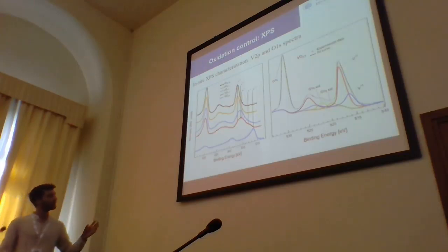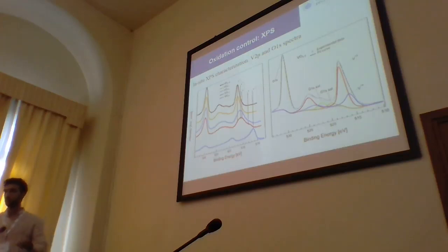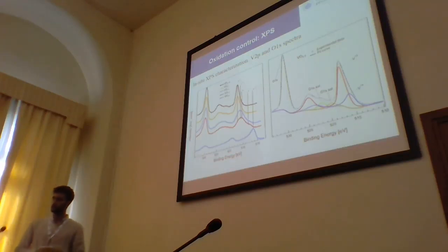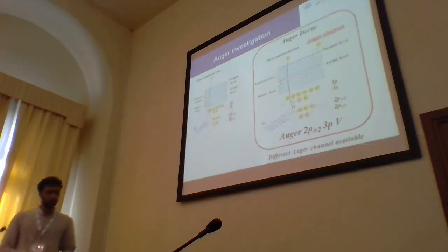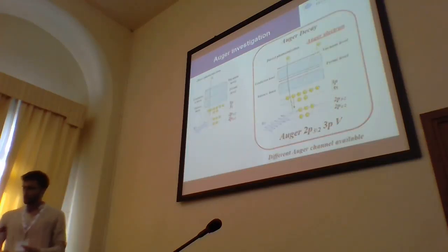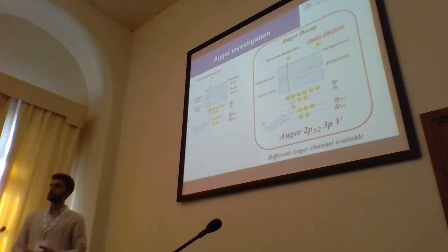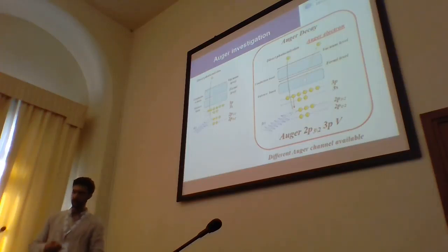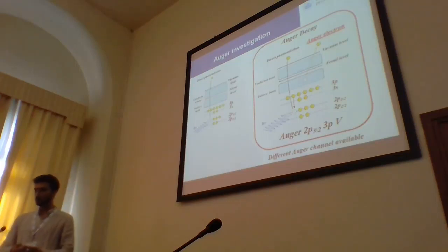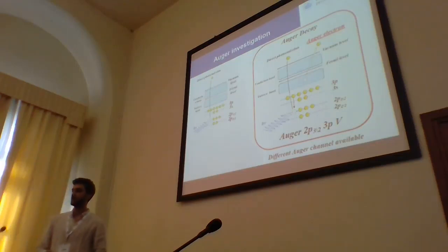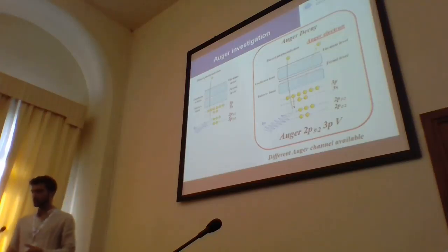So using the cluster source I showed you before and doping with oxygen, I managed to produce vanadium oxide nanostructured films with tunable oxidation state. Tunable oxidation states, I told you, means tunable electronic properties, and in particular tunable valence band occupation. And I probed the valence band using Auger spectroscopy.